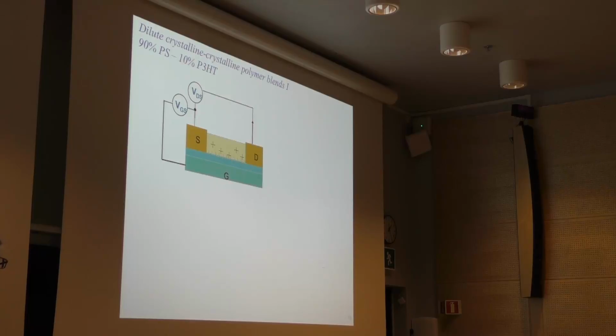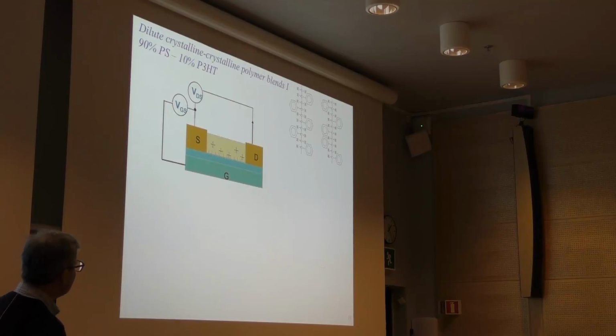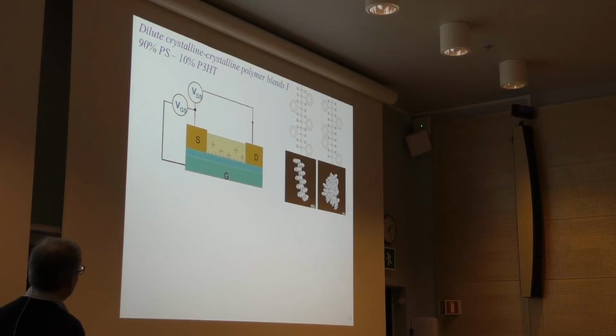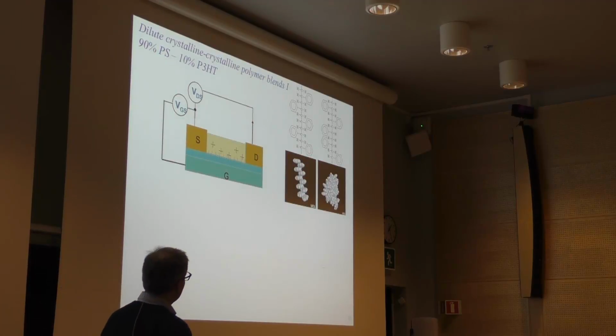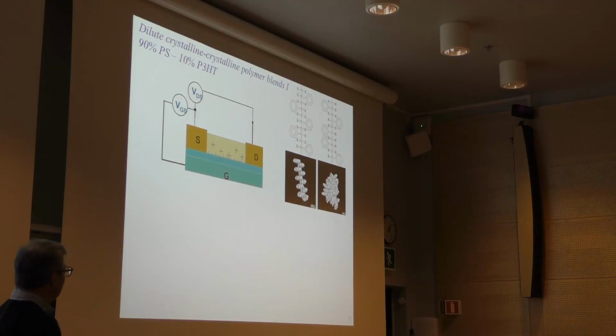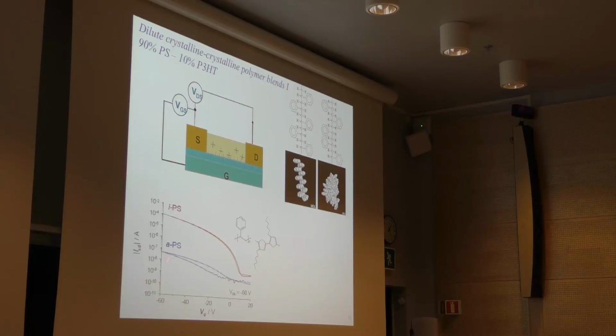Back to this work that I mentioned in the very beginning. In a field effect transistor device, typically like this, we were using different versions of polystyrene. One is the isotactic and the other the atactic variant of those two. And you see that there was also a 10% amount of poly(3-hexylthiophene) mixed into this blend. And you can see that, to our big surprise, there was more than 3 orders of magnitude change in the source drain current in this field effect transistor setup, dependent on whether we were using the isotactic or the atactic